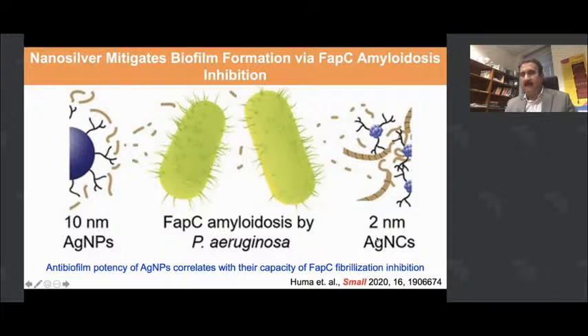In this case, we examined silver nanoclusters of 2 nanometer and 10 nanometer sizes, and we noticed that the 10 nanometer particles, surprisingly, were more efficient to inhibit FAPC fibrillation and to weaken the biofilm.